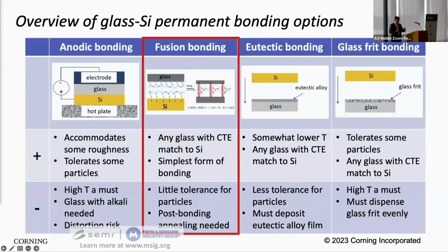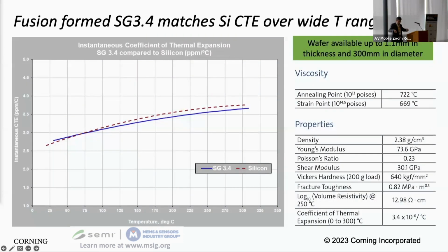Just 2 slides on this other alternative fusion bonding process. And this is a process where we essentially provide a very clean surface, very flat and clean surface. And when the silicon has the same properties, we can bond it without introducing any bond agent, essentially, and there's no voltage involved in the process. So Corning has another glass, also fusion formable, that's called SG 3.4. That has essentially a perfect match to silicon across the very wide temperature. And this means you can bond this glass to silicon at any temperature you want.